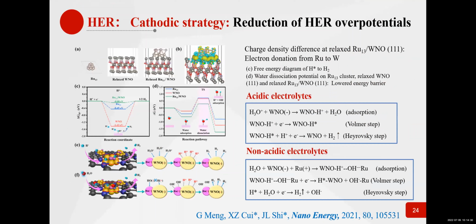And the theoretical calculations show the whole mechanism and why these materials show enhanced activities, especially in alkaline, even much higher than platinum. In the acidic electrolytes and in the non-acidic electrolytes, the reaction pathways can be figured out by the calculations and suitable reasoning.